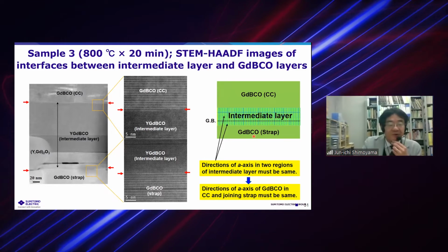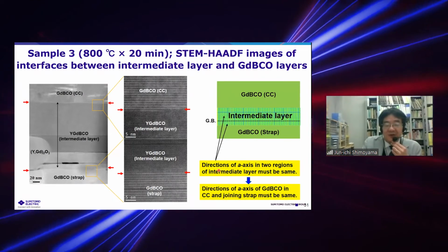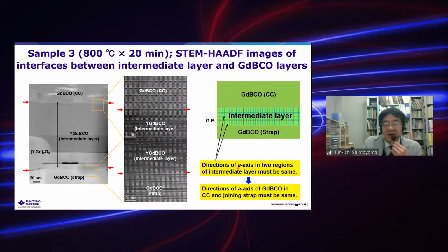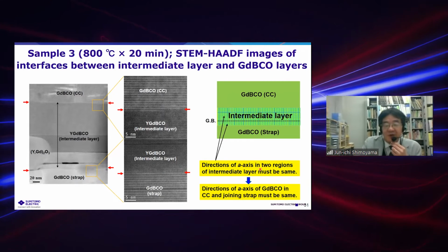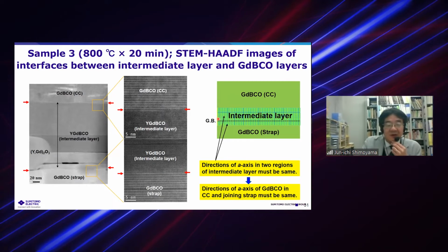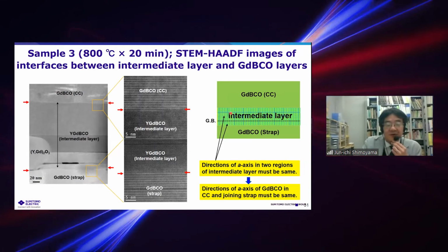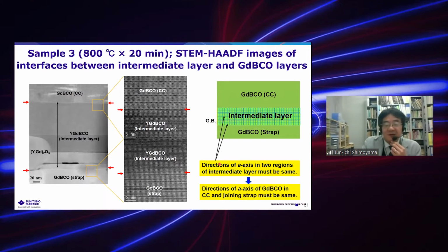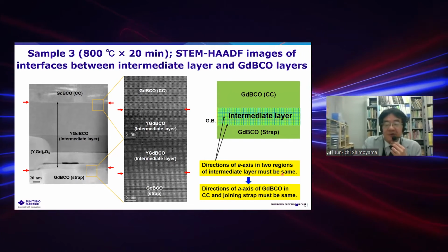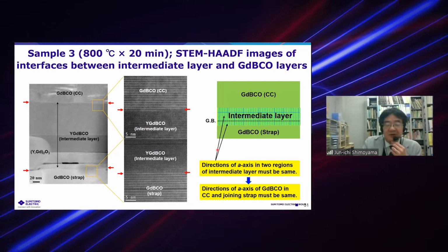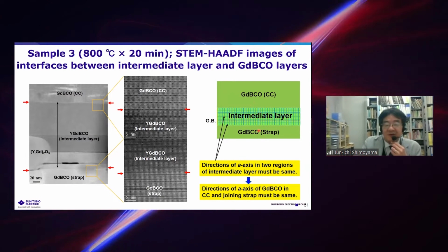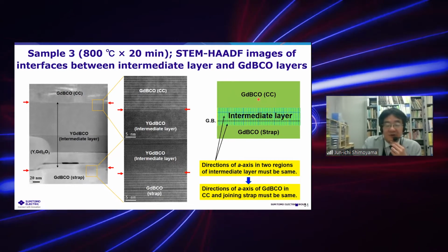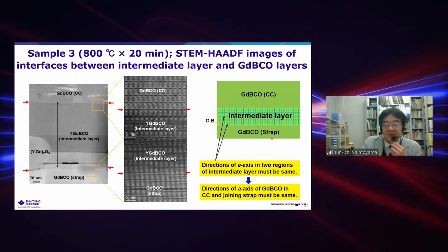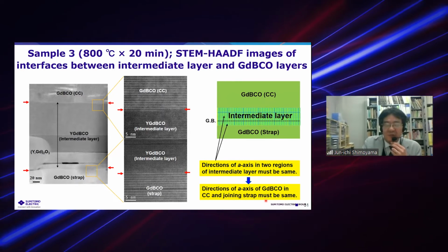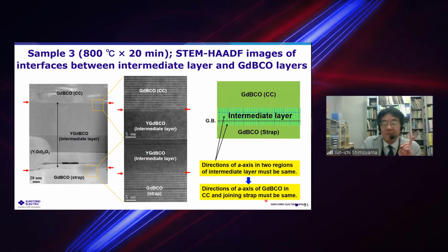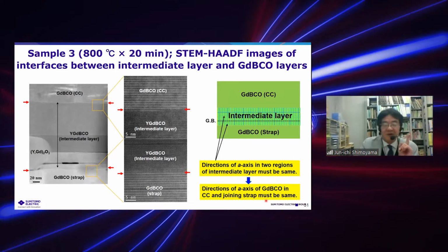So the important point is that the directions of the a-axis of the two regions, the upper part of the grain boundary and the lower part of the grain boundary, must be the same. This means that the direction of the a-axis in GdBCO, coated conductor, and strap must be the same. This is the only one important point we must take into account.